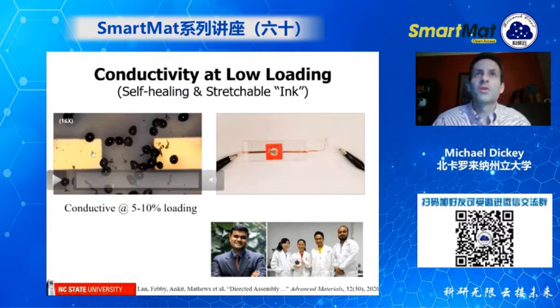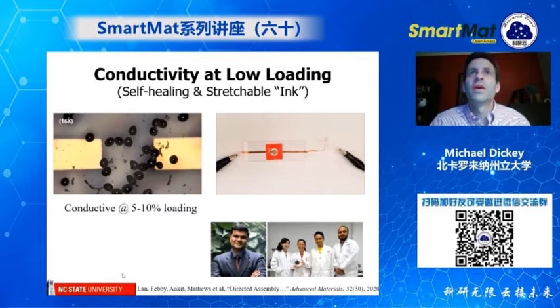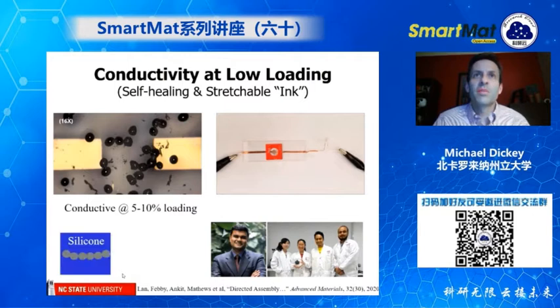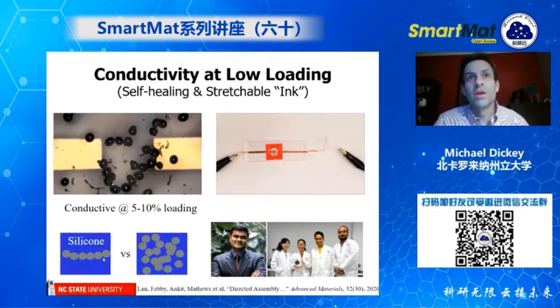Again, these are gold electrodes. The clear stuff here is silicone, and then these black things are the liquid metal particles. When we apply a voltage between here and here, you can see that the particles start moving and they actually line up and they connect because they're liquid. They're easy to connect together. So the beautiful thing about this is we can get conductivity at 5 or 10% loading, whereas typically with composites, you need like 80, 90%, something like that.